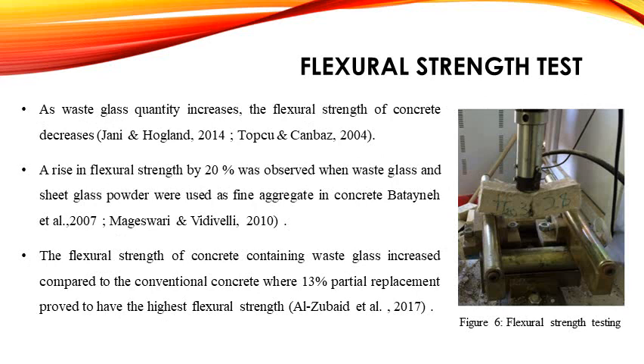Regarding flexural strength tests, results from several studies show that as the waste glass quantity increases, the flexural strength of concrete decreases due to the reduction in adhesive strength of glass particles. Contrary to most research, a rise in flexural strength of 20% was observed when waste glass and sheeted glass powder were used as fine aggregate in concrete. Previous studies show that the flexural strength of concrete containing waste glass increased compared to conventional concrete, where 13% partial replacement proved to have the highest flexural strength at 7, 14, and 28 days due to the increase in the amount of CaCO3 in the concrete.